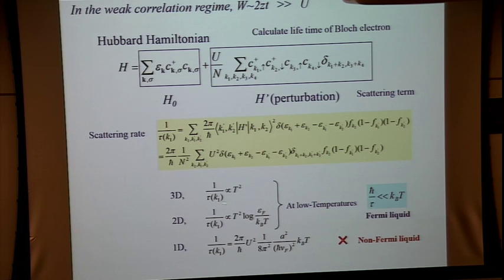So the scattering rate is proportional to the square of temperature, roughly speaking. In the 2D case, strictly speaking, there is a logarithmic prefactor, but its temperature dependence is very weak, so in many cases experimentalists neglect it. Practically, in two-dimensional and three-dimensional cases, the temperature dependence of resistivity is proportional to the square of temperature. This is the manifestation of electron correlation in the weakly correlated regime.